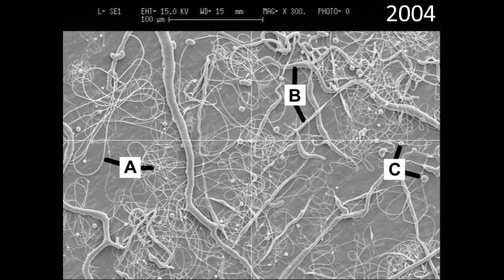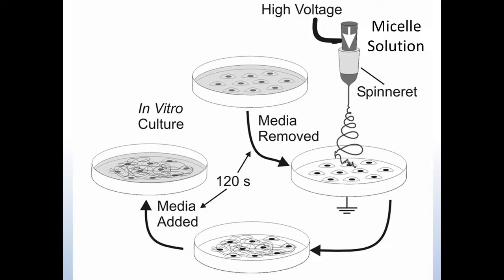If we go back now to 2004, this is what we're making with melt electrospinning. Slight difference. We were getting a mixture of these small diameter solid fibres, which we were really excited about, these large molten fibres, and then these little particles. A lot of the time we spent early on was just trying to work out: it's possible to make these fibres, how do we get that happening all the time? And I was really driven to keep working on this, even though this was the result and it's not particularly impressive. From a philosophical point of view, it was about being able to work with things that can be translated, and it actually started off as a bit of a challenge thrown down by Martin Müller, who was the director of DWI at the time in Aachen.